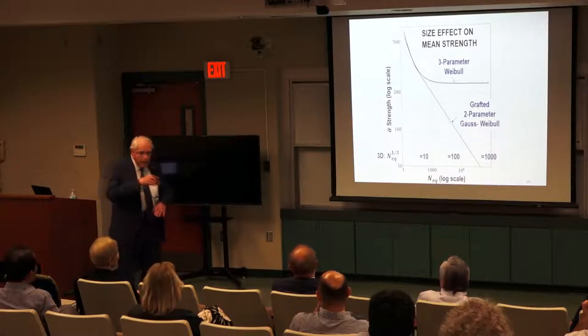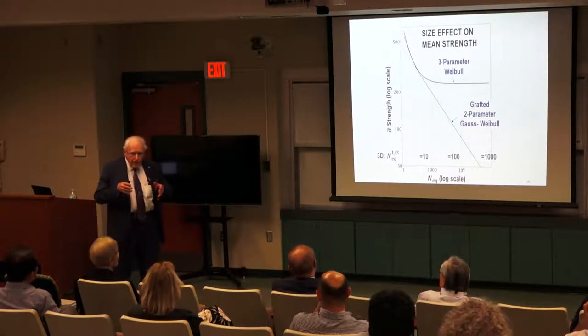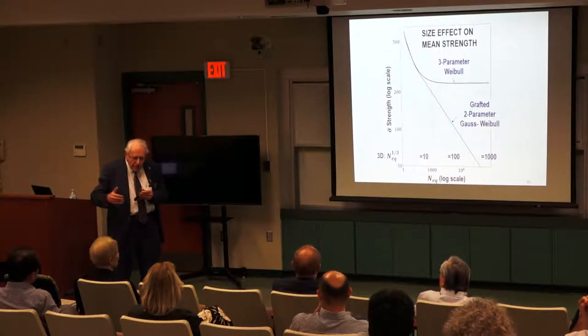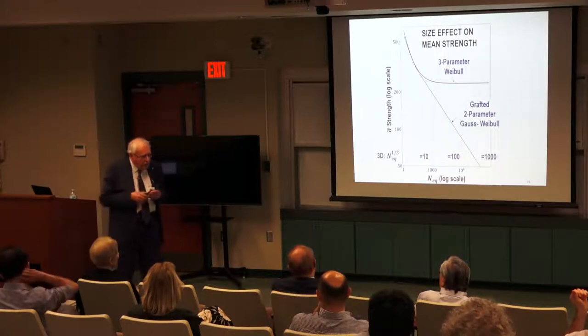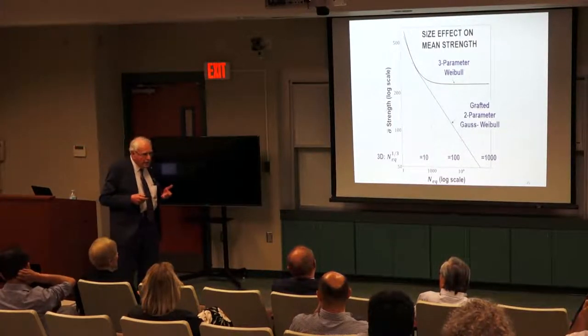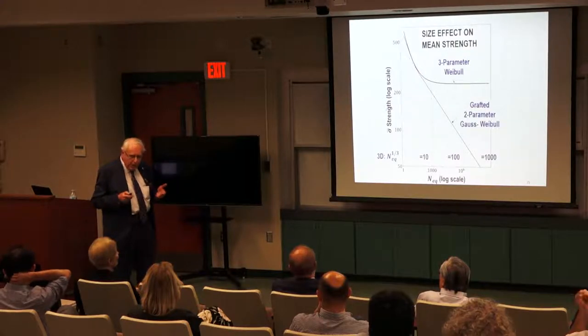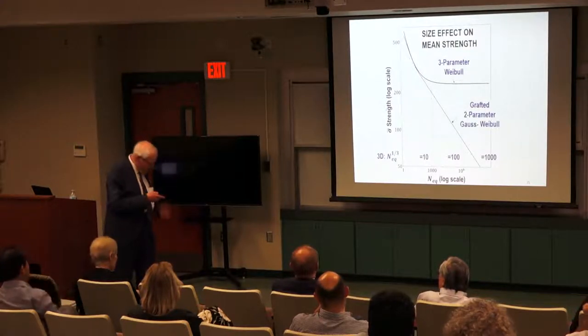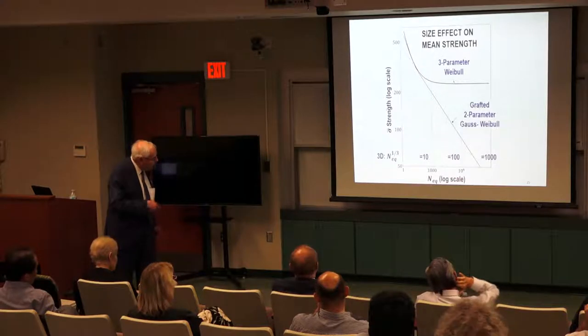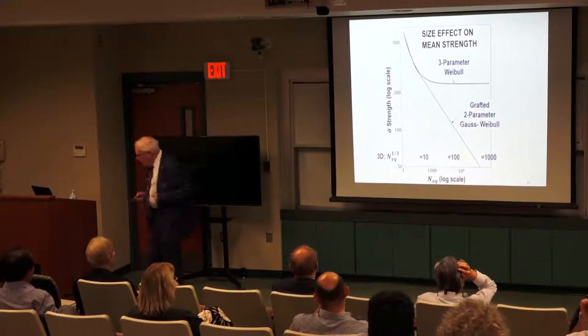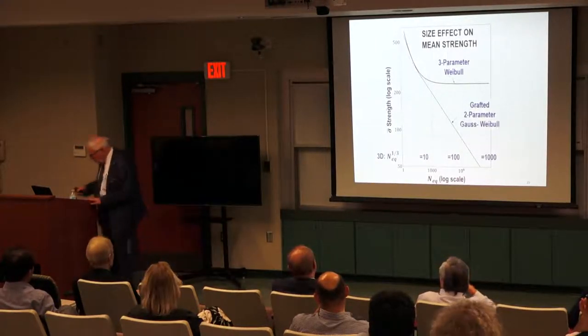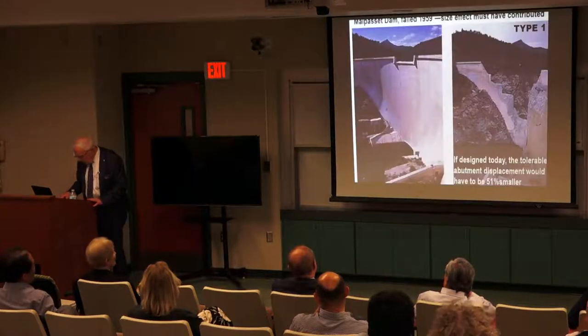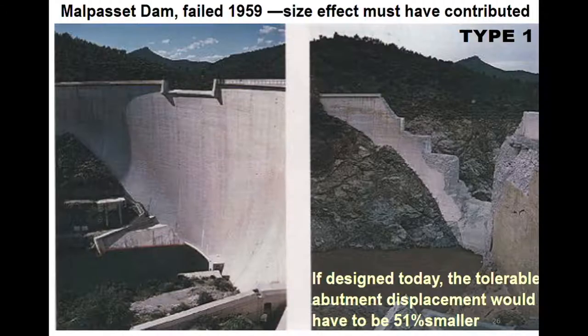But under uniaxial tension, let's say a prism under uniaxial tension would be what? 1,000 RVEs this way, 1,000 this way, also the other way. If the RVE is 1 millimeter or 1 micrometer, you easily realize it. If it's a positive geometry, the structure becomes unstable after the failure of one RVE. That's what's happening, and this is the error. So I mean, this has been published already almost 10 years ago, but there is no response in the ceramics community to this.